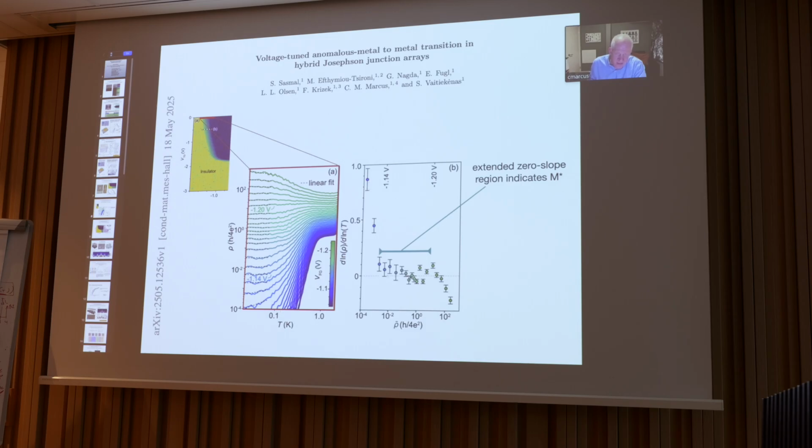That's my definition of a superconductor. Then an extended region that goes on both sides of unity of the average conductance in units of h over 4e squared, hovering around 0 before it peels off in the insulating phase and takes a step up. So the superconductor, anomalous metal, you might say, beginning of an anomalous insulator phase, and then finally the insulator phase is shown in this way with the zigzag.